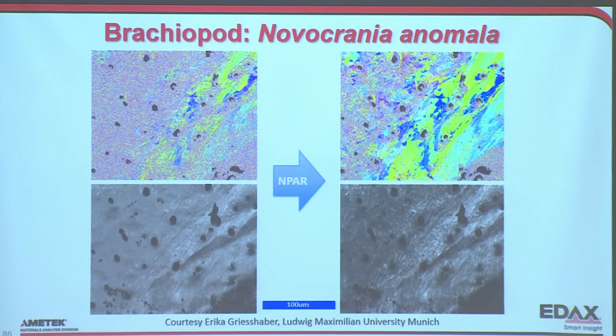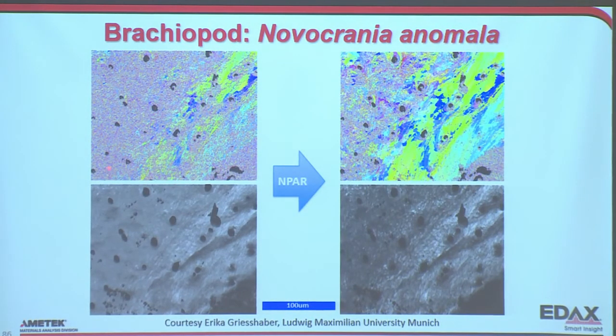Just to show you NPAR on some other samples, this is a brachiopod, a seashell. So here's just regular data and after NPAR. And this sample came to us from Erika Griesshaber at Munich. And you can see, it's interesting to me, not only does it improve the orientation data, it actually shows us detail in the IQ map that we didn't expect to see.